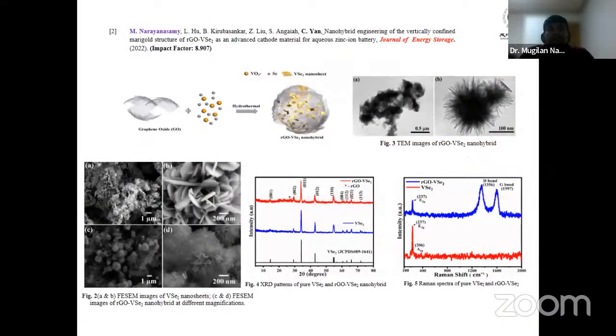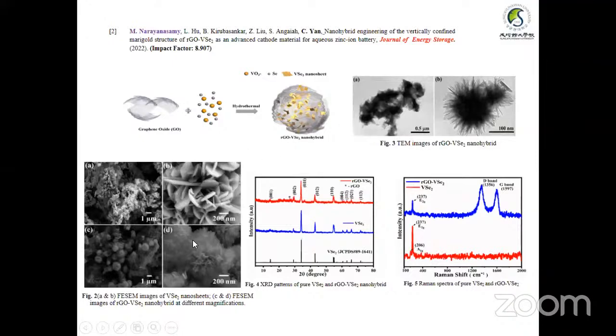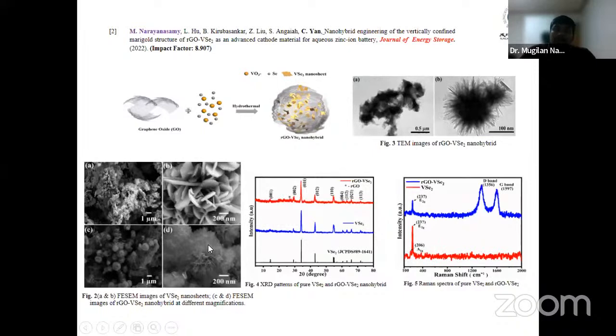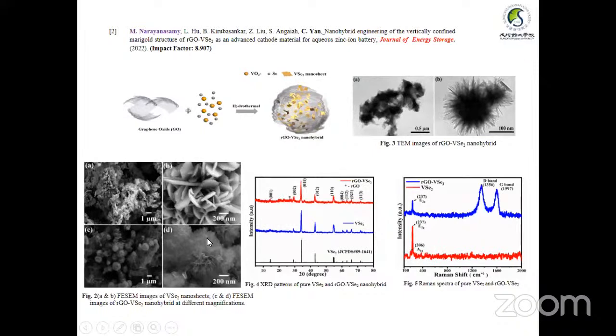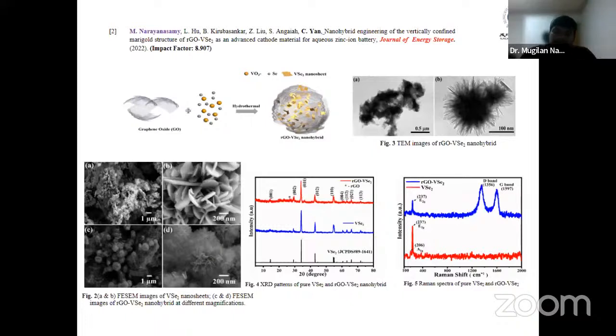In the next work, we will be discussing vanadium diselenide hybrid with graphene oxide. What we have done is we took a graphene oxide precursor and a vanadium precursor and gave them a heat treatment. After heat treatment, I noticed that a marigold-like structure was formed, with reduced graphene oxide acting as a template, giving better performance when compared to the pure VSe2.